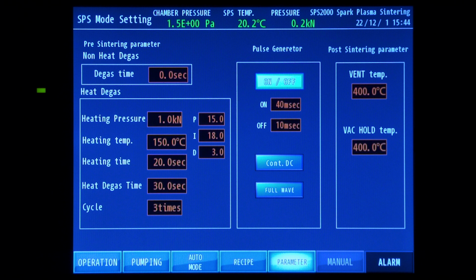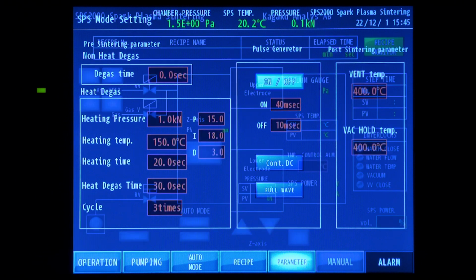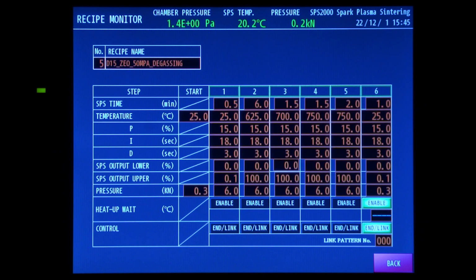The sample here is a zeolite, a very fluffy powder with a lot of surface area and a lot of moisture in it. If I go back to the operation windows, we can take a look at the recipe that we are going to follow. We start by just increasing the pressure to 6 kilonewton, which gives us 50 megapascal, and then we sinter up to 625 degrees, 700, 750, and keep the temperature there. This is rather conventional, but this is now done after the degassing. So I'm back here.